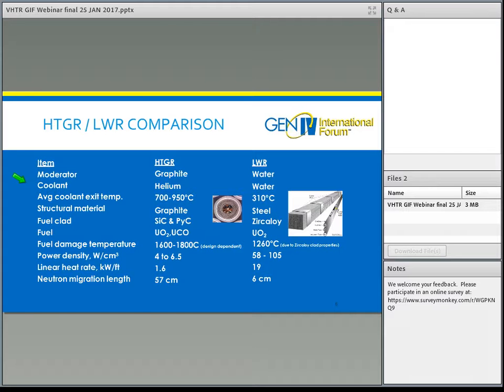The fuel cladding is another major difference. A zircaloy cladding in a light water reactor as compared to a ceramic silicon carbide and pyrolytic carbon fuel cladding in the high temperature gas reactor. The fuel can be the same type of fuel, uranium oxide. We're also looking at a uranium oxycarbide fuel for high temperature gas reactors that I'll talk a little bit more about why some researchers are seeing that as a very advantageous fuel to use.